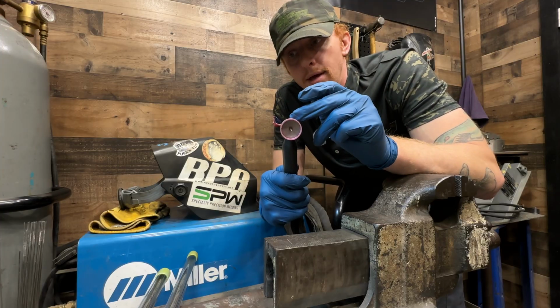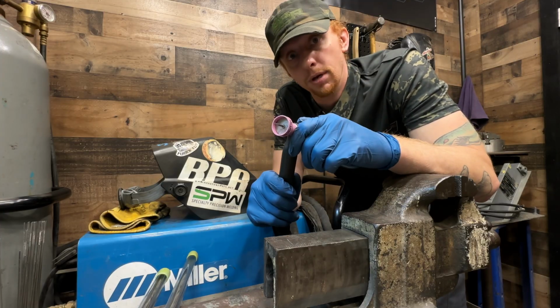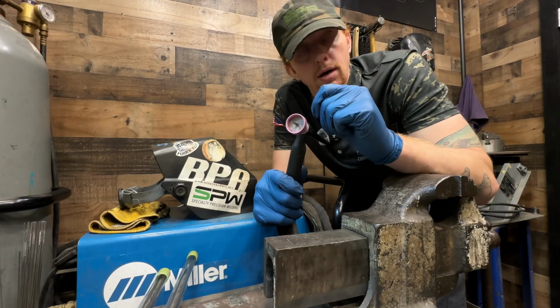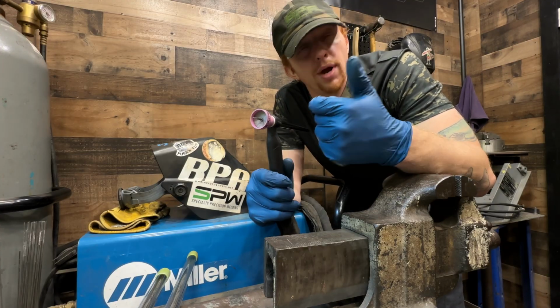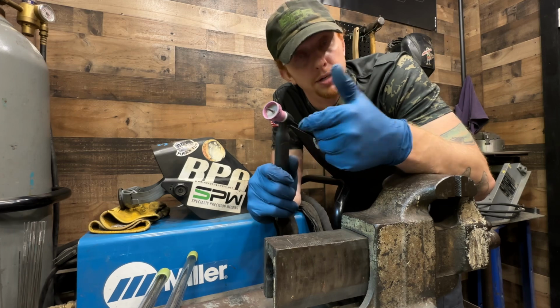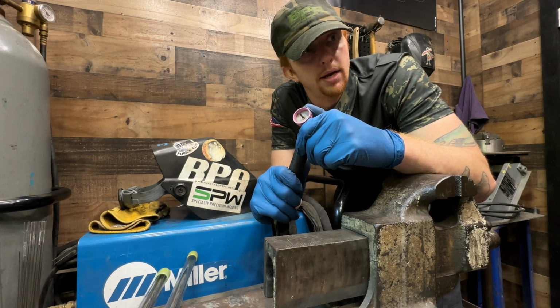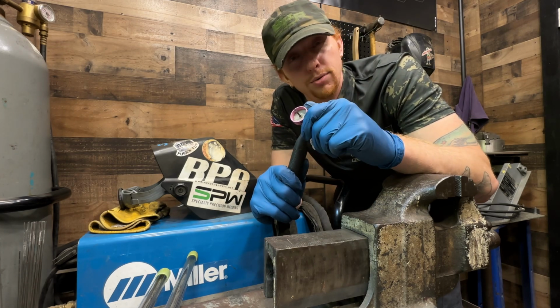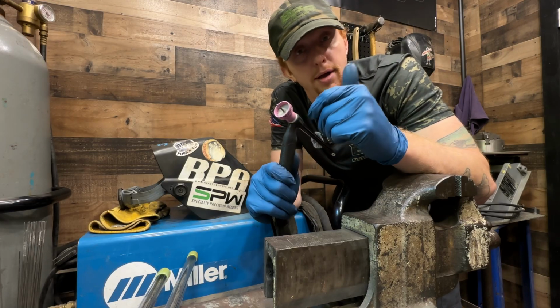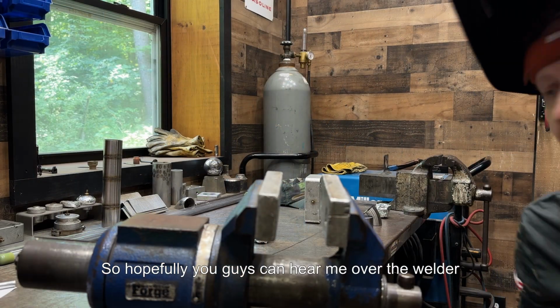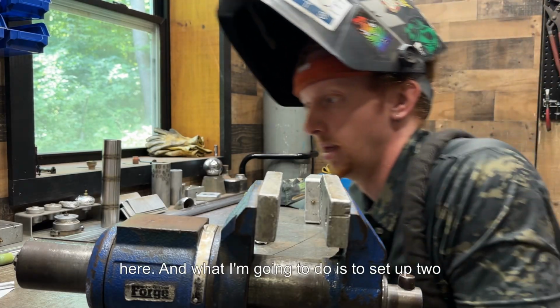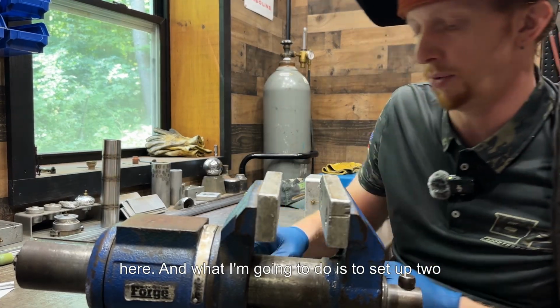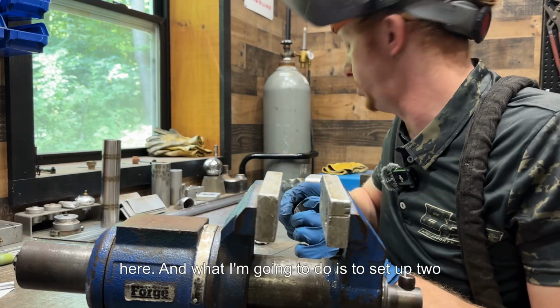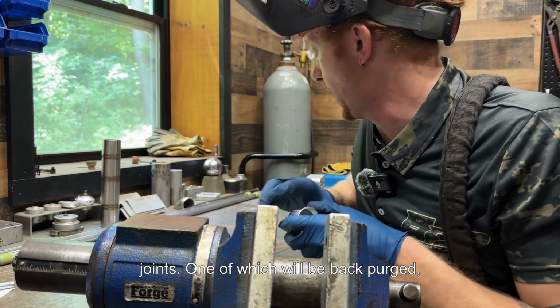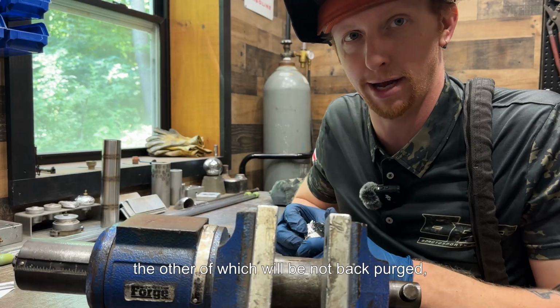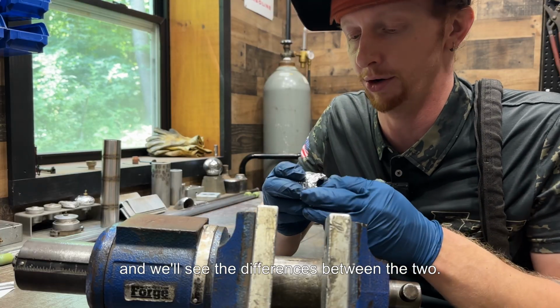So I'll run this cup in somewhere between 30 and 35 cubic feet per hour through the torch. On the back purge side, I'll run around 15 cubic feet per hour constant, continuous through the inside of the piece. And I'll also show you guys what happens when you do not back purge not only the weld, but the tacks as well. So hopefully you guys can hear me over the welder here. What I'm going to do is set up two joints, one of which will be back purged, the other of which will not be back purged. And we'll see the differences between the two.